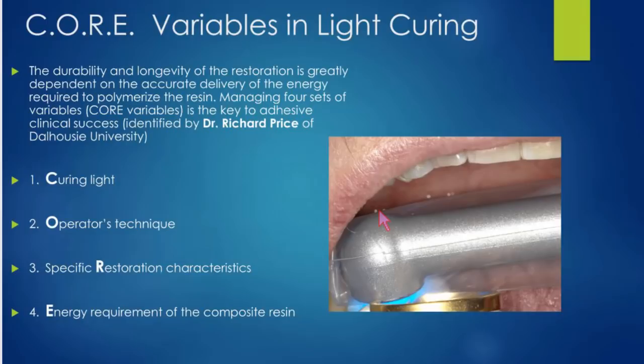The other thing that we have to consider is what are the characteristics of each specific type of restorative material. So some materials out there will talk about having curing depths of 6 or 7 millimeters, which I caution everybody about, because by the time you add your distance with the curing light, the likelihood of filling a really deep restoration and getting it fully polymerized, especially if we go into a darker color or we overfill or don't measure the proximal box, there's just a lot of reasons that we have to be really careful understanding the recommended curing depth for the restorative material and then giving ourselves some playroom.